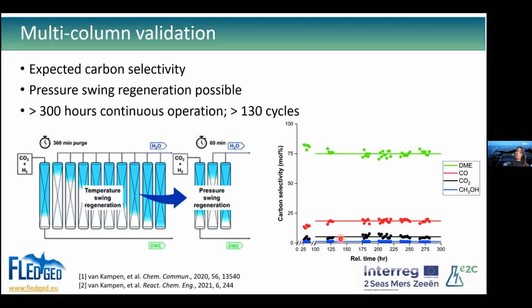We've also tested for a significant amount of time, more than 300 hours of continuous operation and more than 130 full cycles. And you can see the results over here. We can still obtain high carbon selectivities towards DME.